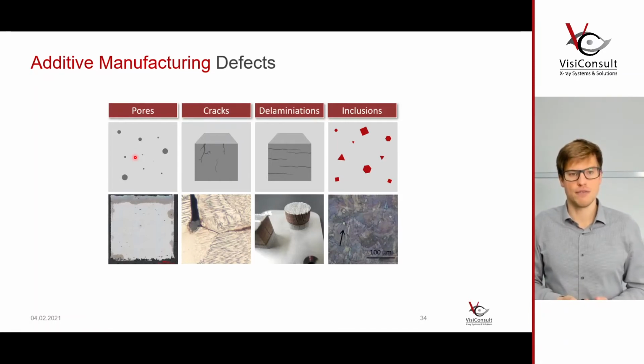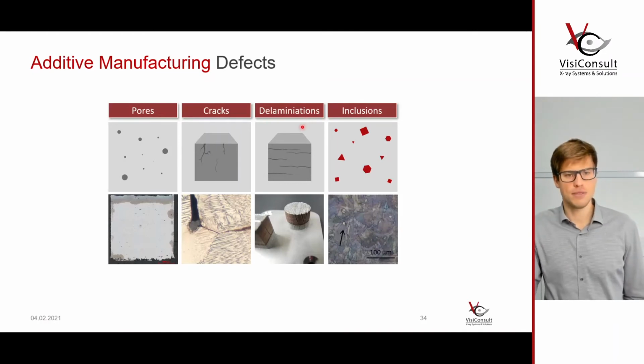Also, cracks originate from different areas. We have a lot of residual stress, a lot of temperature gradients in additive manufactured parts. This can really cause a different cracking image than we've seen in the past. But also delaminations. This is something we've never seen before in most of our manufacturing technologies. But now with additive manufacturing, it can be that laser energy is not quite enough to really fuse the powder of the layer. And if that happens, you have a layer of very thin particles, maybe 30 to 50 micron, that is not molten, so that is not fused completely.